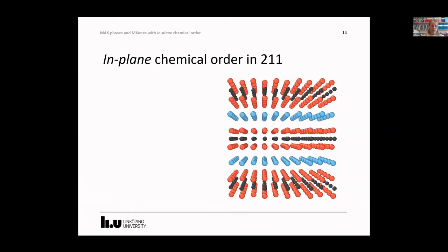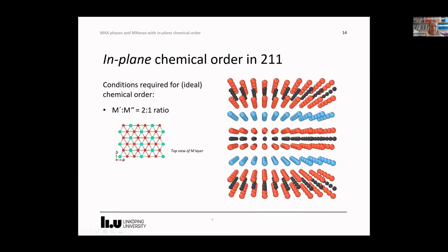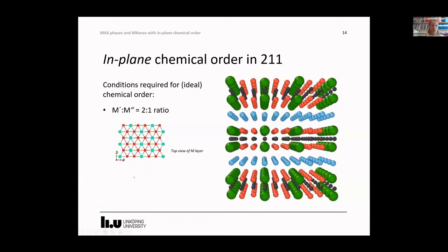In the 211 phases, if I turn to those, there is only one crystallographic metal site, so out-of-plane ordering is not expected. Still, the MAX phase is hexagonal, so if we have an M element ratio of 2:1, we can actually form a honeycomb pattern of the majority metal in the M layer and have in-plane chemical order. This is what such order looks like if we have a top view of the M layer, and this is what it looks like in side view.